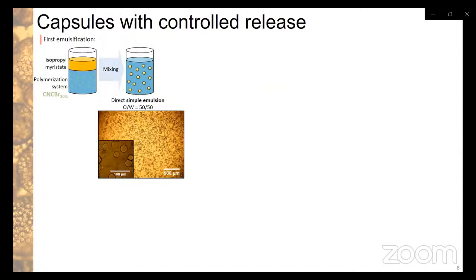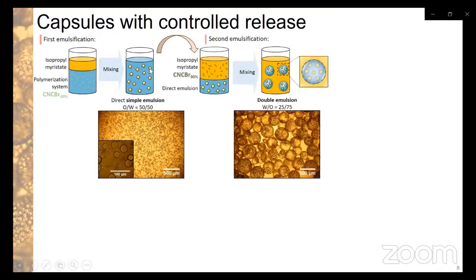Finally, the last system we wanted to focus on was capsules with controlled release. So these capsules were obtained by taking double emulsions as templates. To make the double emulsion, we just work with a two-step emulsification. The first emulsification step is to realize the direct simple emulsion, so an oil in water emulsion. This time we use the hydrophilic CNC, so with a low modification rate. So we disperse the isopropyl myristate into the polymerization system with those hydrophilic CNC, and we used this first emulsion as the dispersed phase for the second emulsification, taking this time hydrophobic CNC, and we obtained double emulsions, oil in water in oil.